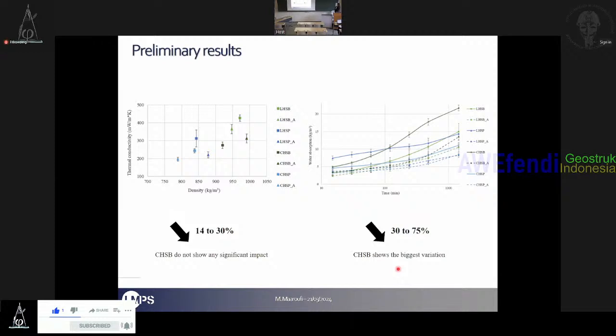These results may seem inconsistent with porosity that really increased after the aging, even if I didn't present the results. But actually, what we can see in previous works also is that the increased porosity is the intraparticular porosity, and what's really working with the water absorption is the capillary porosity. So it's quite different, and we think that the aging may create new intraparticular porosities, but may crush existing capillary porosities, which could explain the increase in the total porosity value, but the decrease in the water absorption.